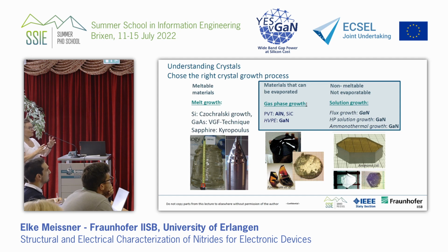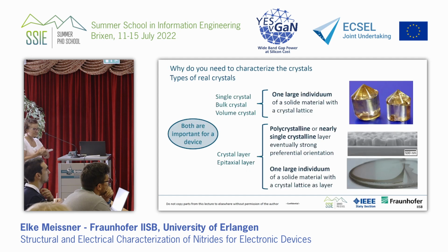And those are all comparatively difficult methods compared to classical crystal growth of a semiconductor like gallium arsenide or silicon. So this is much more difficult. From a crystal grower's point of view, we say, okay, the nitrides really pose a big challenge to the crystal growers. And this also means that it's even harder to grow the crystals larger and thicker, such that you achieve more wafers out of a crystal more efficiently. So keep this in mind.